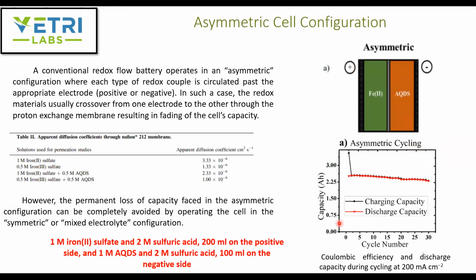This paper mostly focuses on how you can change the cell configuration, and how you can avoid the crossover. When you use an asymmetric cell configuration, where on one side you have completely Fe ion solution, and on the other side you have the AQDS solution, you call that an asymmetric condition, where each type of redox couple is separated on a different side. In that case, you always have a crossover from one electrode to the other through the proton exchange membrane, resulting in the fading of the cell's capacity.